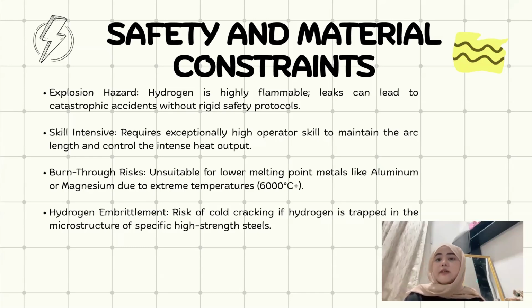Fourth is hydrogen embrittlement. Finally, there is a severe metallurgical risk of cold cracking. If atomic hydrogen gets trapped within the microstructure of specific high strength steel as the weld metal cools down, it compromises the structural integrity, causing the metal to become brittle and prone to fracturing.